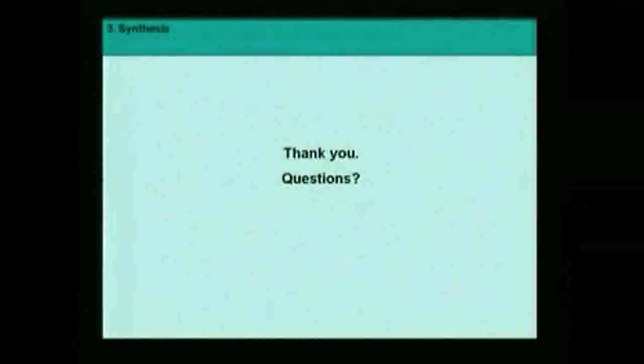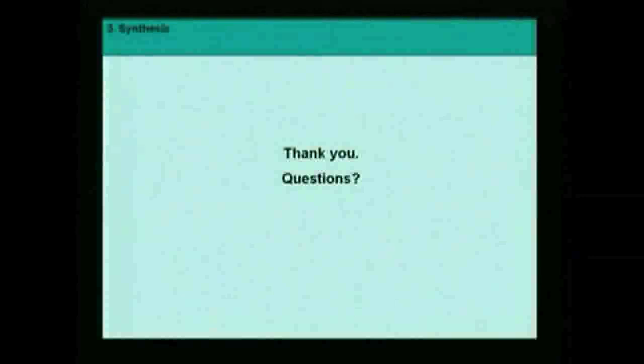Oh, it's a difficult question. So to get either single-wall tubes or multi-wall tubes is essentially a question of particle size. So it's not a question of the element, at least in CCVD. Most important is to control the size of the particles. So to control the size of the particles, you need to control the initial amount of catalyst on the support. This can be done by several techniques, like spin coating, like vacuum evaporation, like sputtering, like ion beam sputtering. So it's mainly about that.